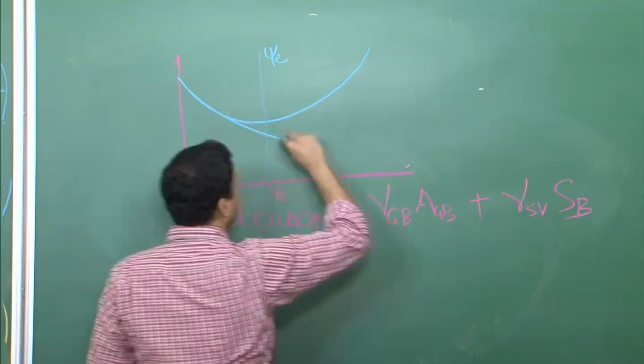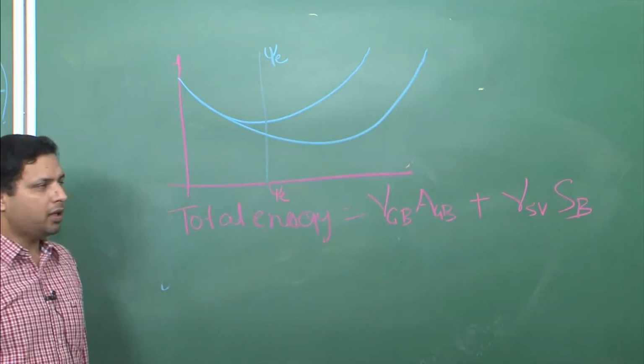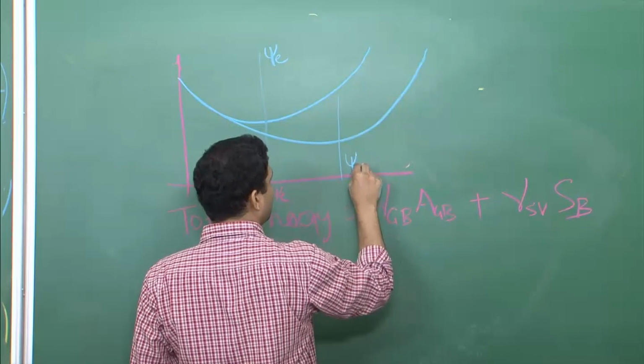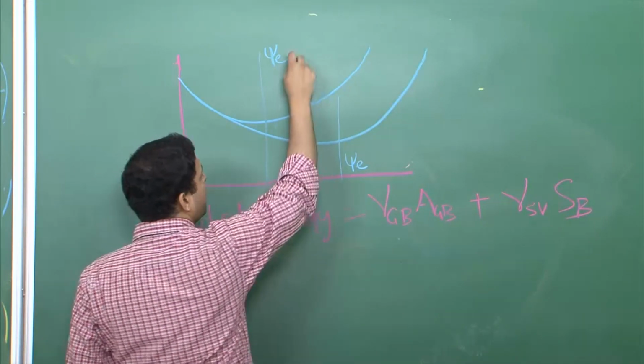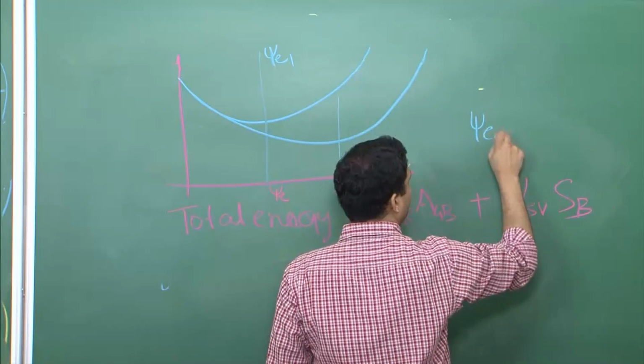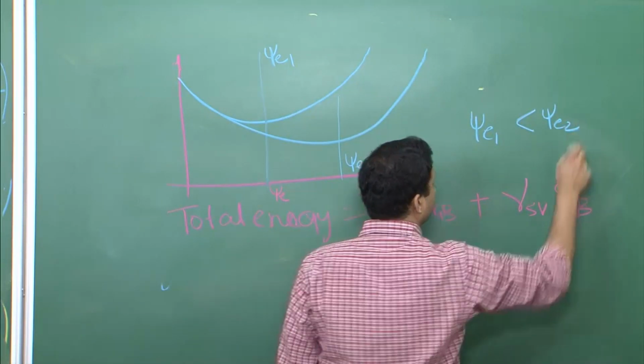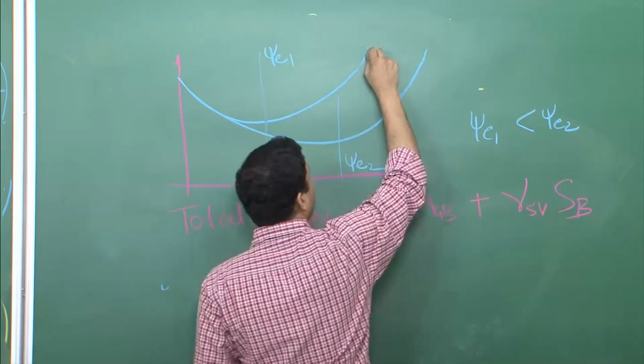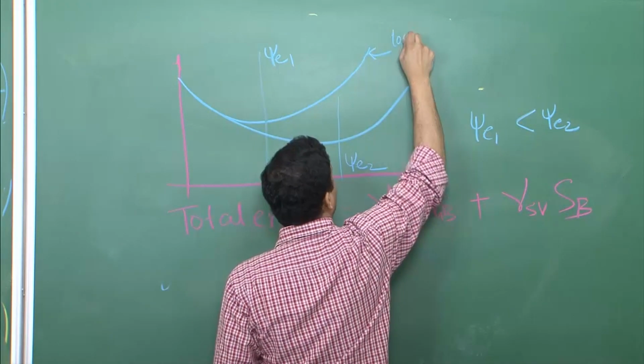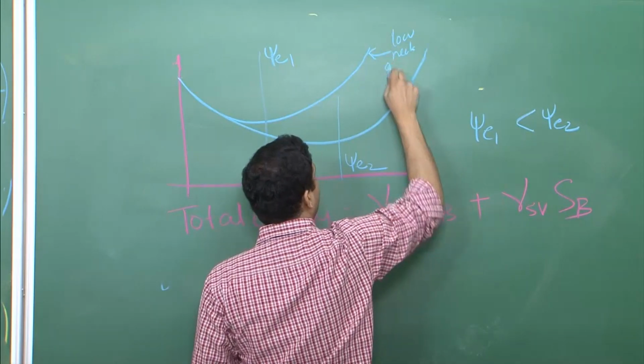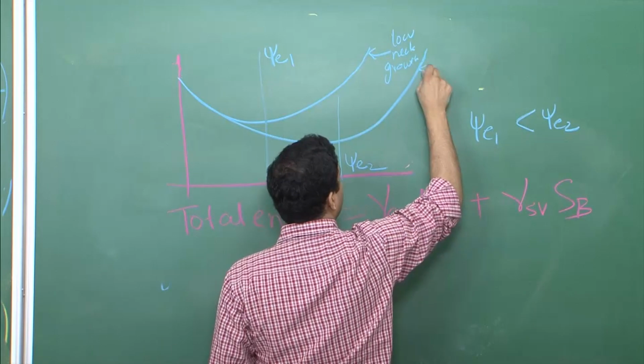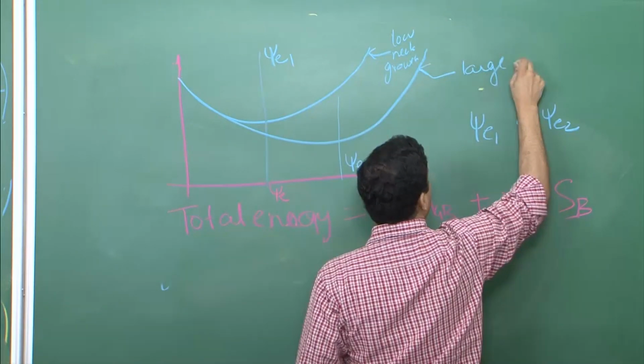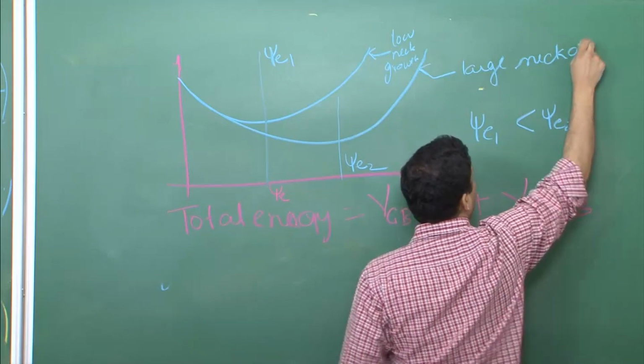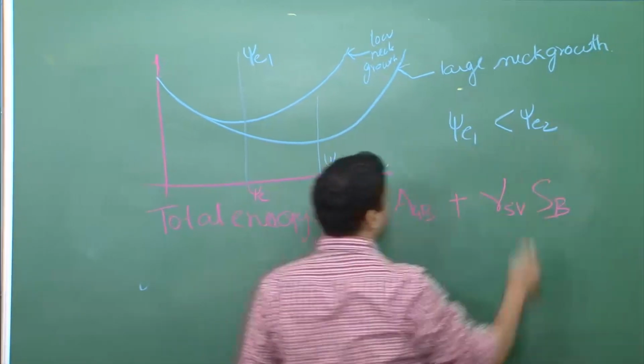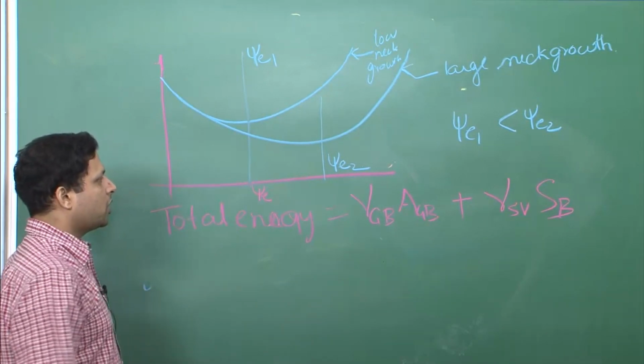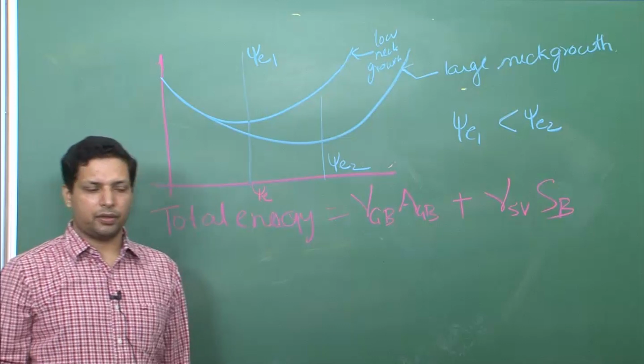In some other cases, if for example the material was different, you may get a different psi E. And what do these mean? So, let us say this is psi E1, this is psi E2. So, psi E1 is less than psi E2. It means that in here the neck growth is low neck growth, and in this one, large neck growth. So, this is how your plot will look like. The higher the psi E value, higher is the neck growth.